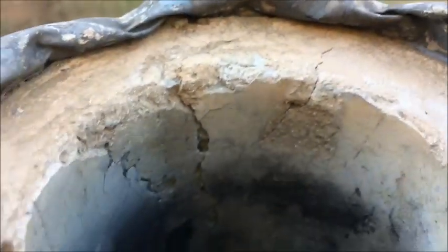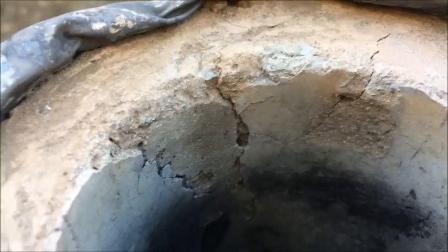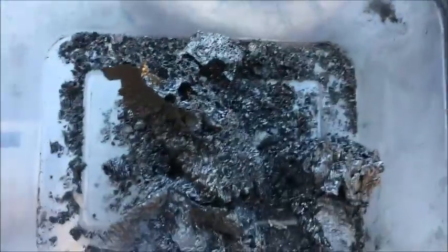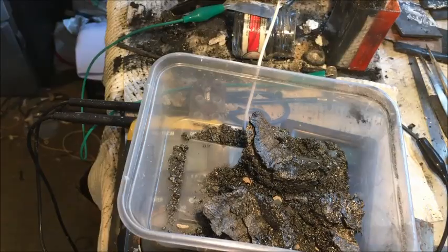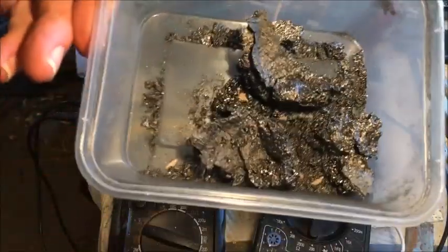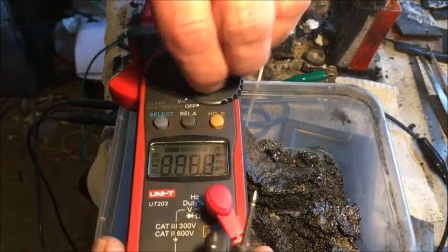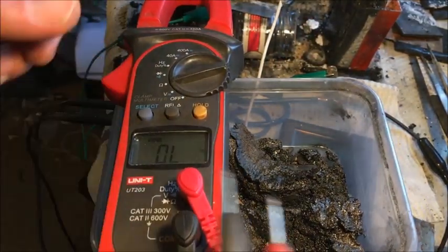Okay, the calcium aluminate crucible withstood the temperature. It's got a crack there, but it's not too bad. I had to destroy the outer shell to get it out though, but that won't matter too much, and that's the yield we have. I'll take it inside and we'll check it with the magnet. Okay, the yield's not so great. That's the total yield. So we'll check the ohms again while I'm in here.